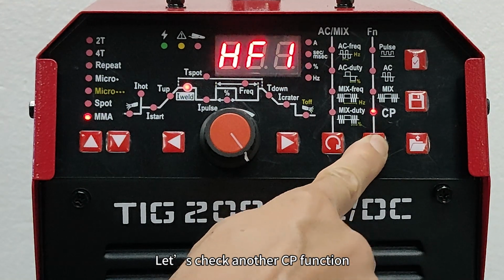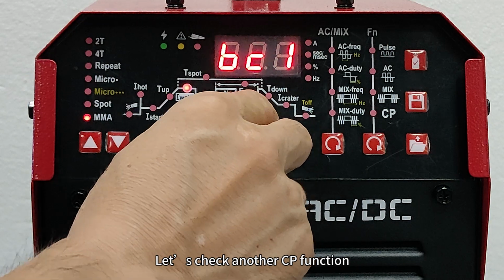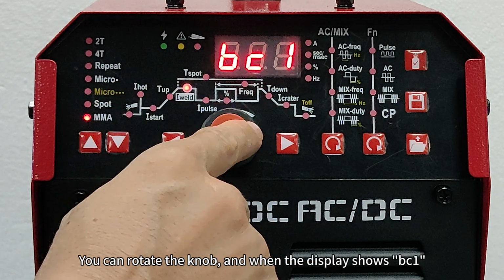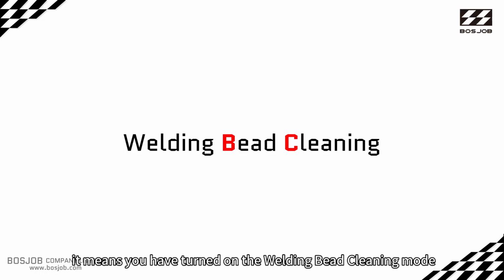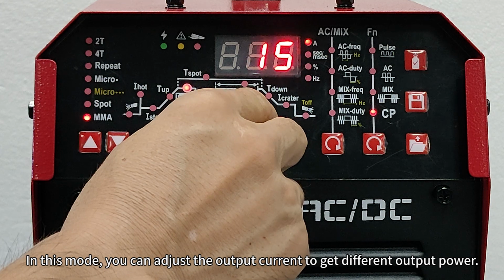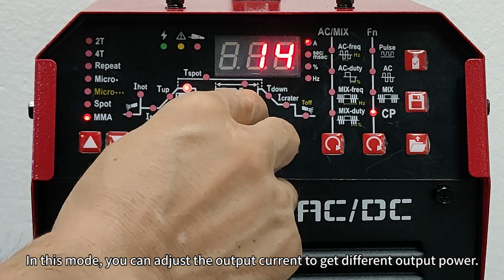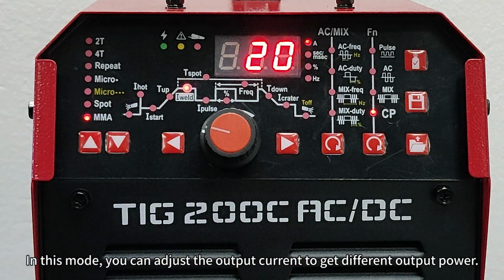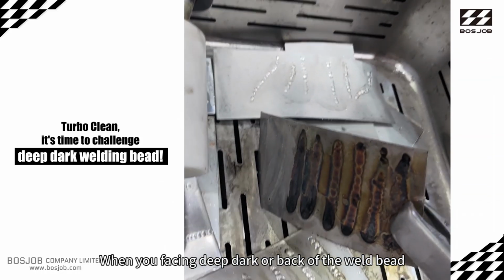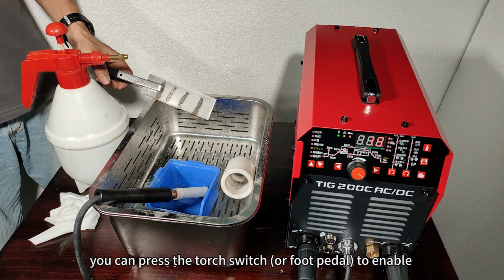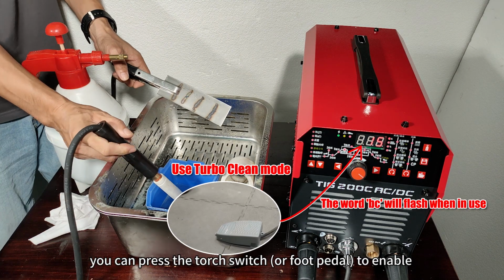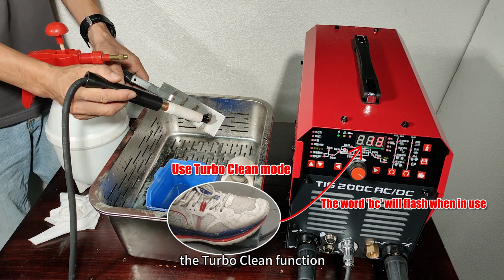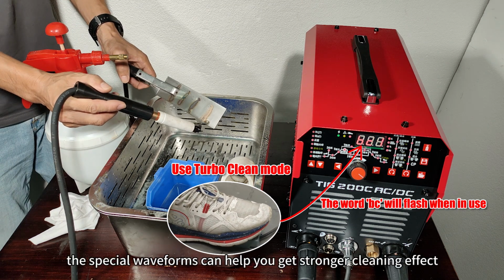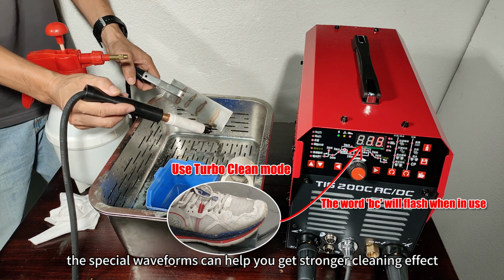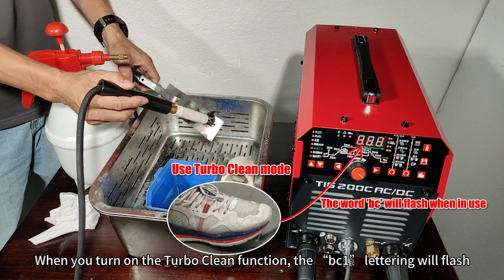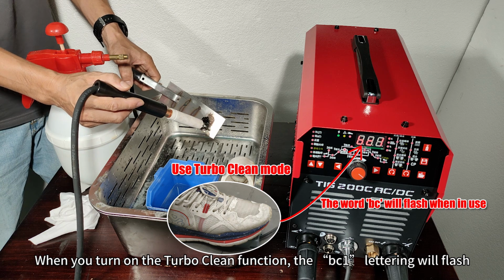Let's check another CP function. You can rotate the knob, and when the display shows BC1, it means you have turned on the welding bead cleaning mode. In this mode, you can adjust the output current to get different output power. When you're facing deep dark areas on the back of the welding bead, you can press the torch switch or foot pedal to enable the turbo clean function. Special waveforms can help you get stronger cleaning effect. When you turn on the turbo clean function, the BC1 lettering will flash.